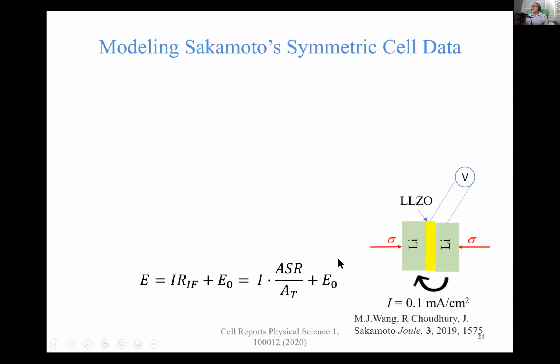So anyway, we built this model, and we decided to apply it to some symmetric cell data that Jeff Sakamoto had just reported on. Here's his symmetric cell. It's got lithium electrodes and some LLZO solid electrolyte in between. The experiment is run entirely in mode where he's stripping from the right side and plating from the left side, and he's got adjustable stack pressures shown in red. And then he can measure the voltage drop across this region.